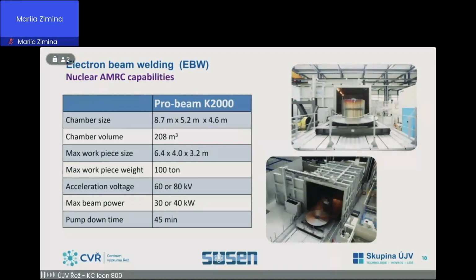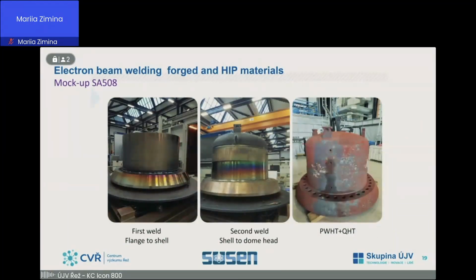In the picture, there are some data about current capabilities in the field of electron beam welding at the Nuclear AMRC. They have a relatively huge vacuum chamber with volume 208 cubic meters. They can handle pieces with weight up to 100 tons, and they use a 40 kilowatt electron gun. In this picture, you see welded lower assemblies for the NuScale power reactor vessel with welded joints flange to shell and shell to dome head.